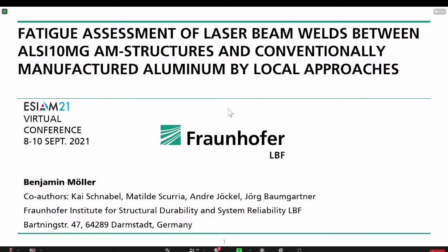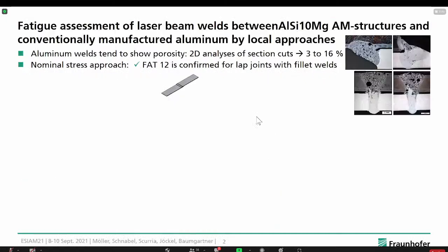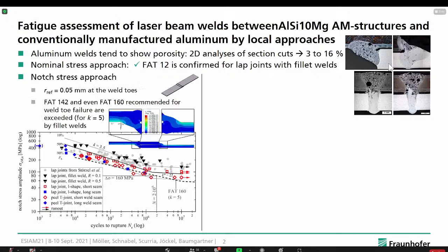So therefore we set up an experimental and numerical test program using lap joints, which are laser beam welded between additively manufactured material here in the upper part and conventionally manufactured aluminum 6082 in the lower part. We had a test program with fillet welds and welds which run through the two materials. In the first step, we just evaluated nominal stresses in this case.